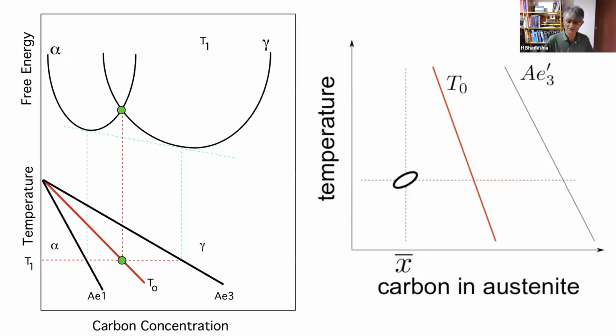Well, this is a free energy curve at a particular temperature for ferrite and austenite. And if you want to find the equilibrium compositions of the two phases, you draw a common tangent here because that gives you equal chemical potentials in both phases. And that defines the equilibrium phase boundaries here and here at that particular temperature. But there is this point which doesn't appear on the phase diagram, where the two phases have identical free energy and chemical composition. Now, what that means is that to the right of that green point, I cannot get diffusionless transformation because that would raise the free energy. But to the left of that point, it is possible in principle, albeit with a smaller free energy change. So the locus of these points on our phase diagram defines a T0 curve, to the right of which diffusionless transformation is thermodynamically impossible, and to the left, it is possible in principle.